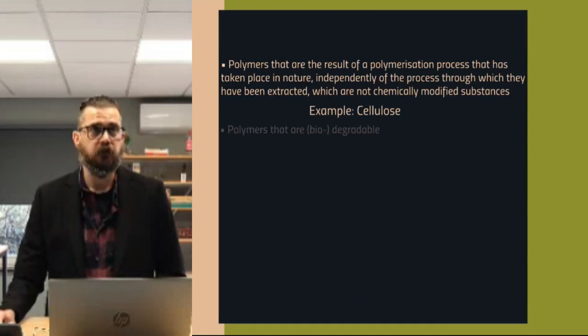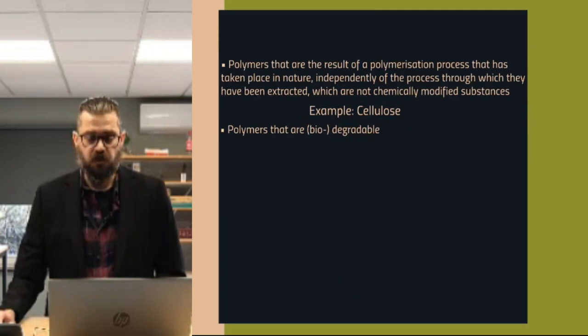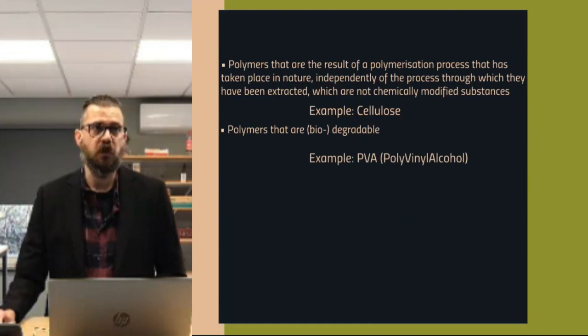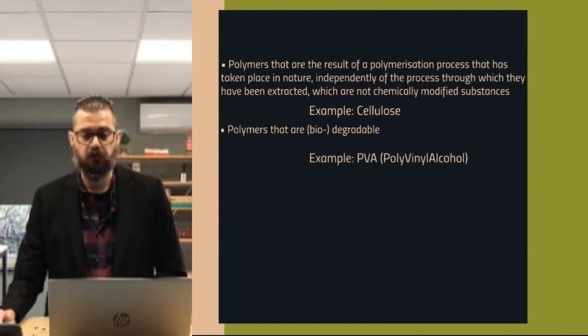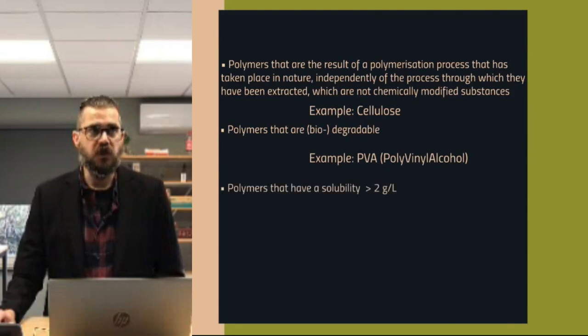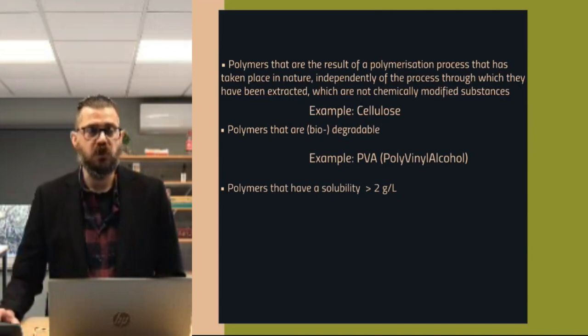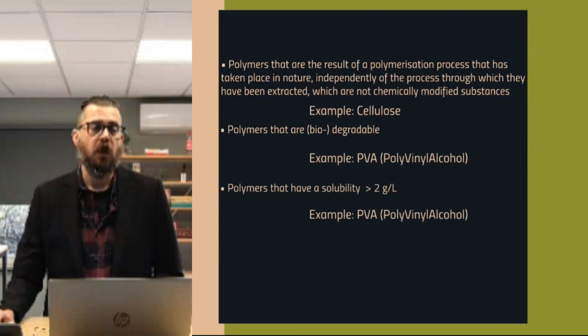Cellulose is a natural polymer. Polymers that are biodegradable are also excluded. There are specific rules to see if a certain polymer is biodegradable, described in Annex 15 of the same regulation — for instance, PVA or polyvinyl alcohol. The next exclusion is solubility: if you can prove that the polymers have a solubility larger than 2 grams per liter, you can exclude them from the definition of microplastics. PVA is an example here as well.